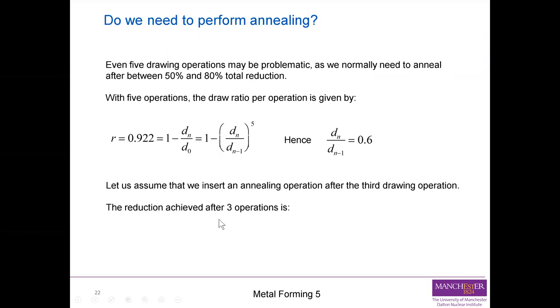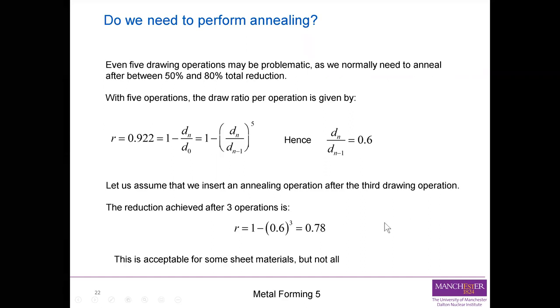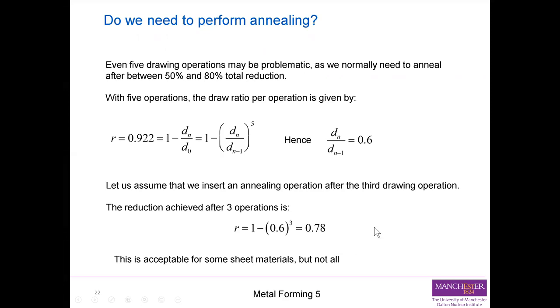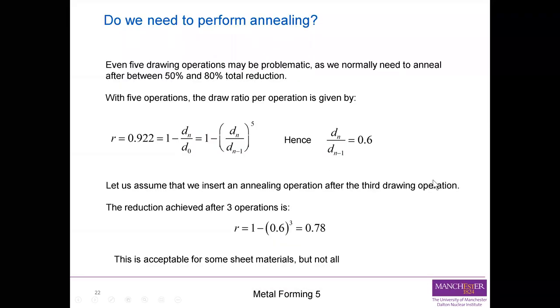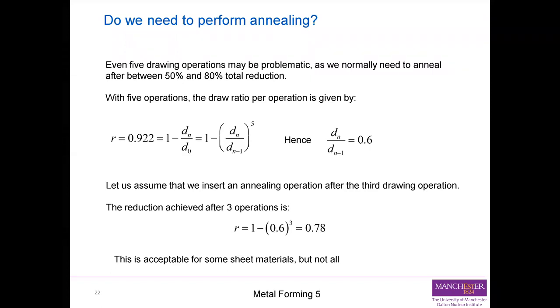So let's assume that we insert an annealing operation after the third drawing operation. The reduction achieved after three operations is 1 minus 0.6 to the power of 3, which equals 0.78. So this is 78%. This is acceptable for some sheet materials, but not all. And this brings us to the end of this worked example.